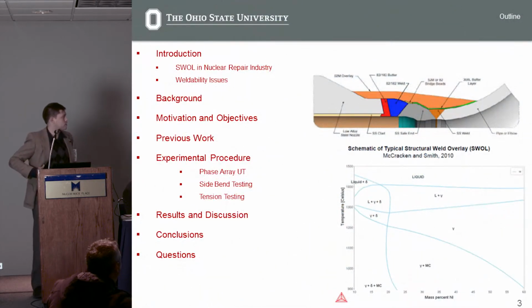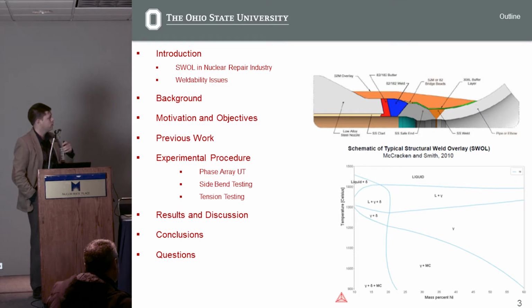So the introduction is, in the nuclear industry, in pressurized water reactors, there's a low alloy steel nozzle that's butt welded using filler metal 82 to some stainless piping on the other side here. And time has proven that the filler metal 82 is insufficient to prevent stress corrosion cracking in the weldment. What I just did is explain this diagram here.